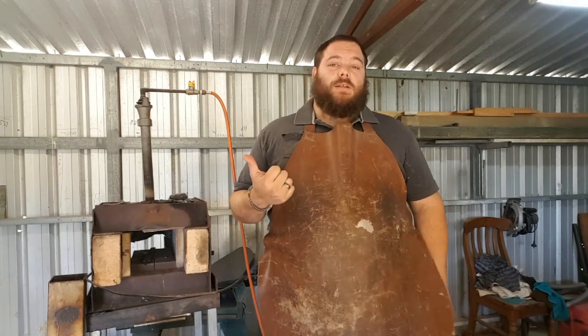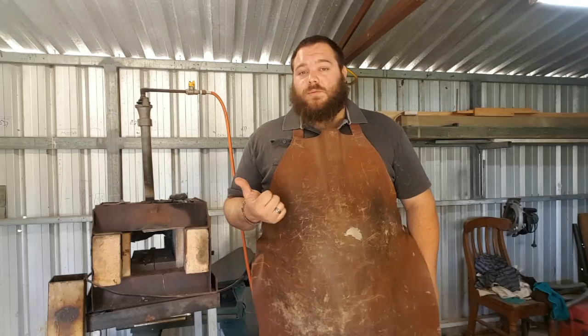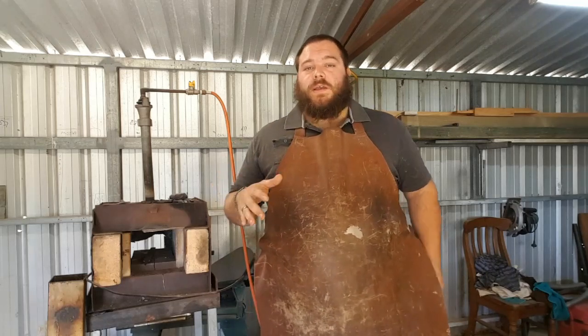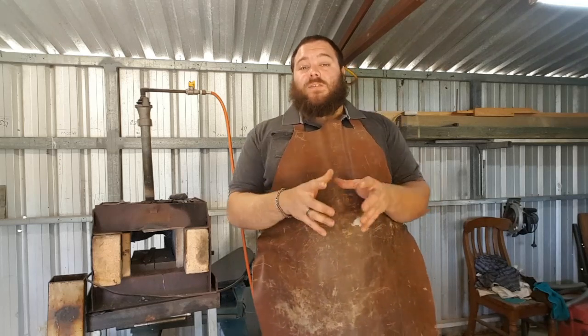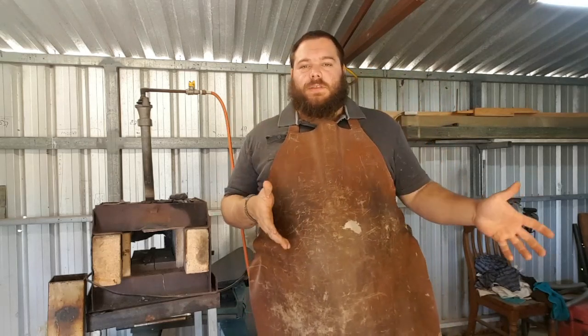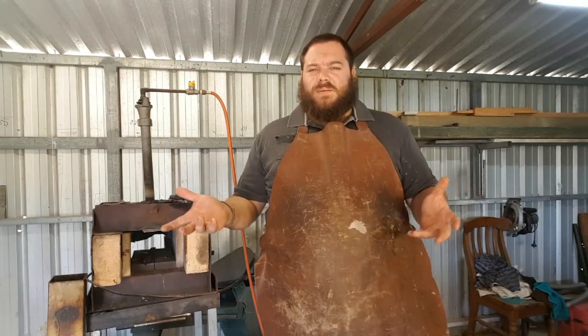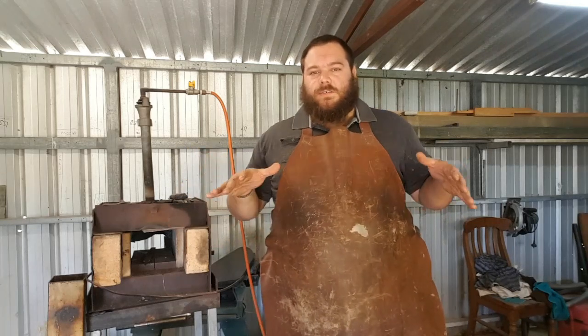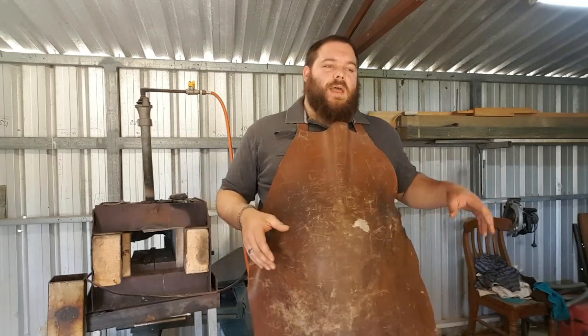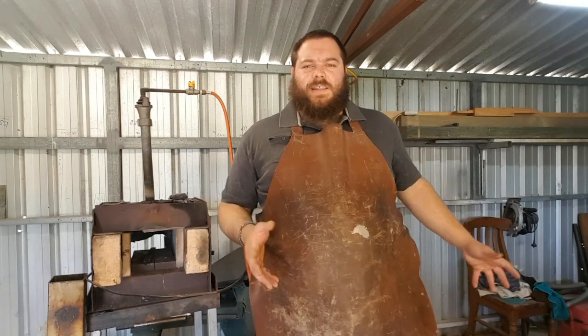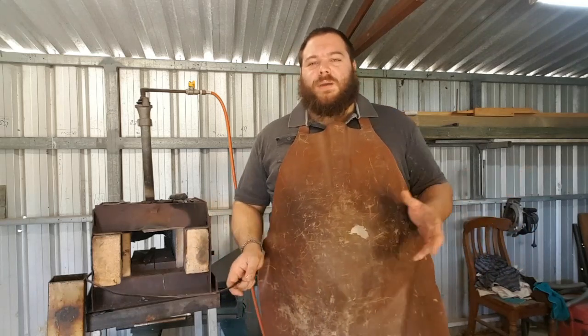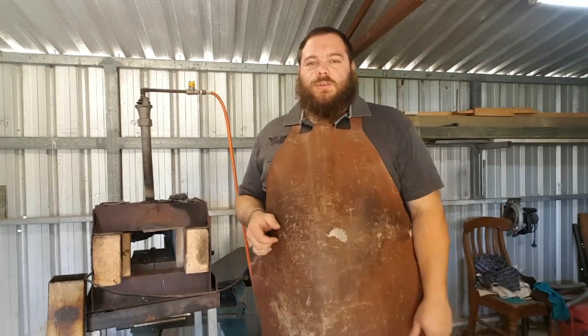The other thing you can do with brine to make it even better is to add a little bit of dish soap, which is a surfactant which kills the surface tension of the water, which means that it's going to cling to the steel that you put in there a lot faster, which means it's going to cool it down even quicker. Some people refer to that as super quench. The dish detergent or the laundry detergent that some people use is a surfactant that kills surface tension, and that just helps it cling better. I don't tend to use that in my brines because salt and water just tends to do the job for me, but if you really need that extra level of hardenability, then you can do that.